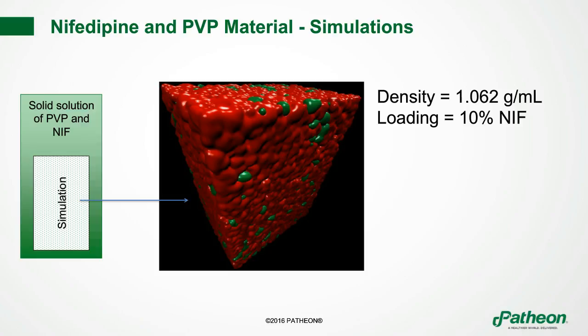And so this tells us that not only are we simulating the system accurately, but that the charge model and the force field and the molecular dynamics engine that we're using are leading us to results that map to what we see experimentally, which tells us that we can take this forward into systems where we don't have experimental data so that we can extrapolate and predict on new systems.